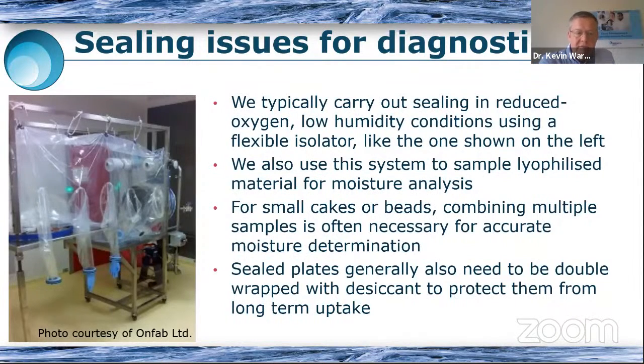We also use this kind of nitrogen tent to sample for moisture analysis and DSC and the other things that we might apply after freeze drying. If we've got small cakes or small beads, small freeze dried materials, then we often have to combine multiple samples. So it's always best to manipulate them in a controlled environment so that you don't subject them to uptake in atmospheric moisture. And again, we double wrap things with desiccant in this environment.